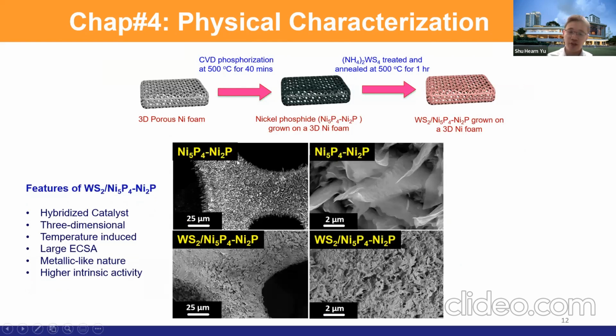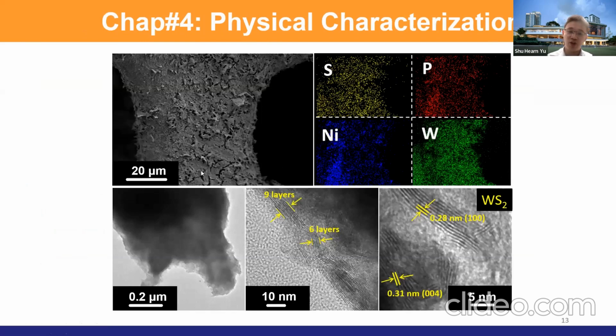Before the annealing process, before the WS2 begins to anneal, we have the 3D structures, and this is the vertical standing nickel phosphide. And after the annealing process, the morphology changed a lot, but surprisingly, we find that the surface area increased. Okay, so this is the structure of the WS2 and nickel phosphide hybridized electrode. You can see the sulfur, phosphorus, nickel, and tungsten are distributed quite uniformly. And under TEM, we can see that there are WS2 layers, 9 layers, 6 layers. So they are close to the edges, so the edges are still very active for the HER reaction.